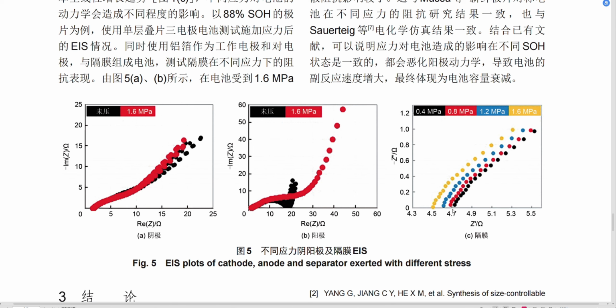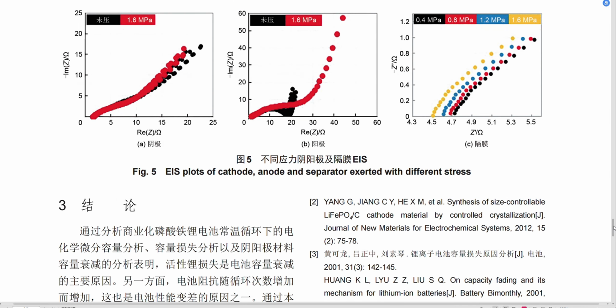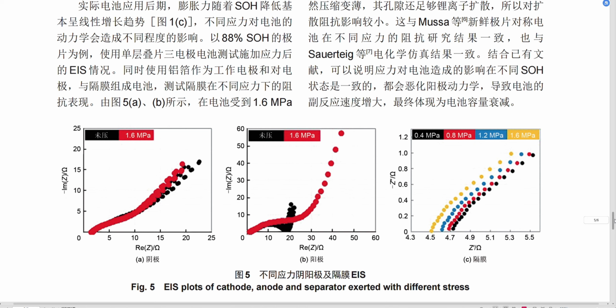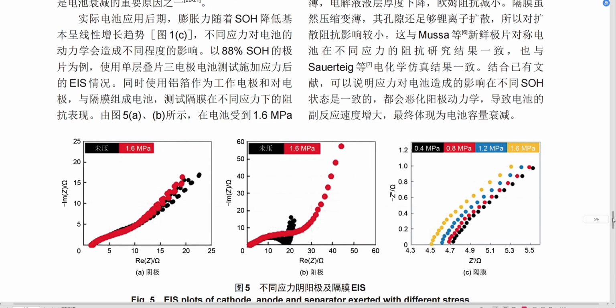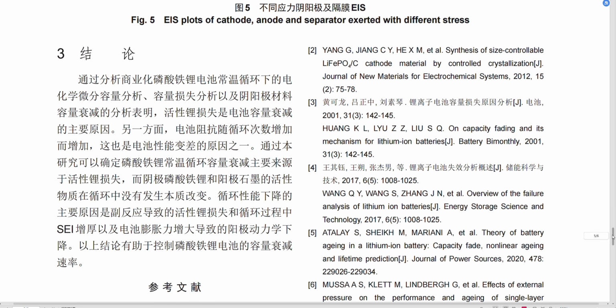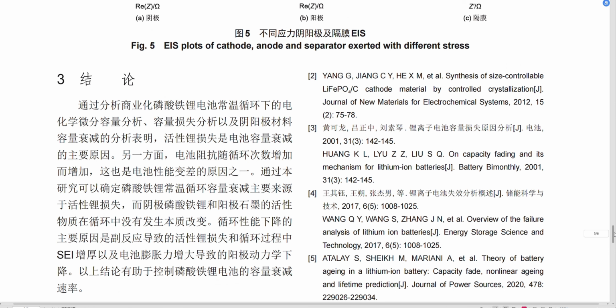For the separator part, you will see the plot shifting to the left side for the first point, which is an internal resistance part, rather than the charge transfer part. So the major charge transfer differences between with and without external pressure come from the anode side. So this is another support for the argument that during cycling, the rate performance differences mainly come from the anode side.